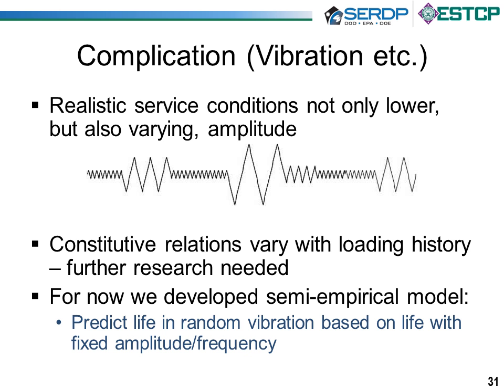A complication arises if you look here. Really, what happens in real life does not look like a mild accelerated test or anything like that. Your airplane takes off, you get strong vibration during takeoff and mild vibration while flying and things like that. You get a lot of variations in the loading amplitudes here. And that complicates matters because in that case, the constitutive relations, the deformation properties, keep varying depending on the specifics of that loading history. So your properties afterwards are different because it saw some high cycles or not. And so there's a lot more work that needs to be done to predict this in the usual fashion.